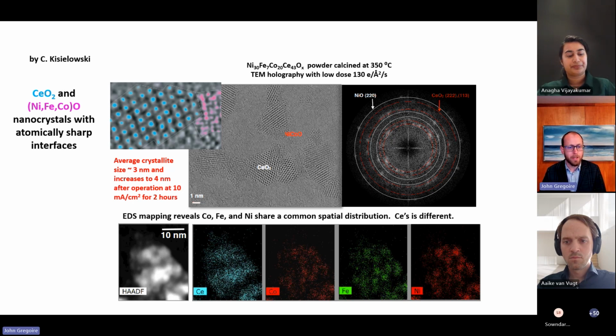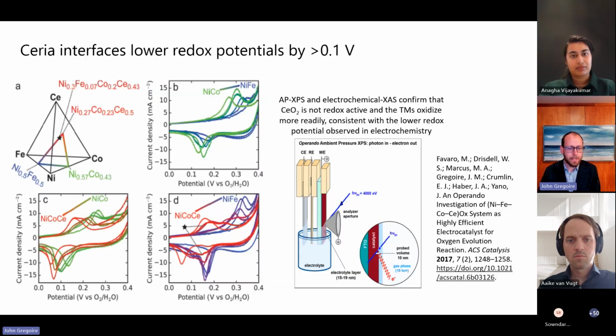These atomic resolution images showed that everywhere we looked, while we have 4 metals in the system, they're not all in the same phase. The ceria segregates into fluorite ceria particles and has atomically sharp interfaces to rock salt mixed transition metal oxide crystals. That's corroborated by the composition maps and also that X-ray absorption study from the previous slide. So we said, all right, if the cerium isn't being incorporated into this phase, how is it changing the overpotential so dramatically, particularly at low current densities?